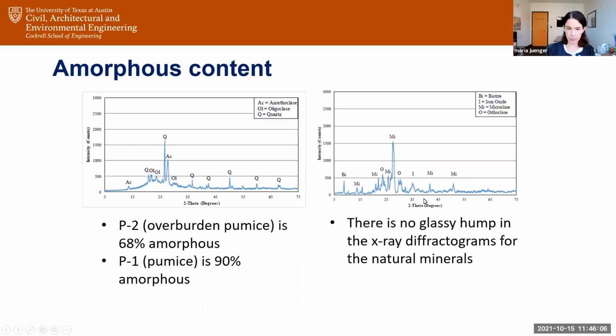And if you look at the X-ray diffraction data from these types of roofing shingles, if you have a pumice, you get this little glassy hump here. So you have some crystalline phases in there, but you have this little hump that indicates you have amorphous material. In these roofing shingles, there's no amorphous hump. There's no glass.